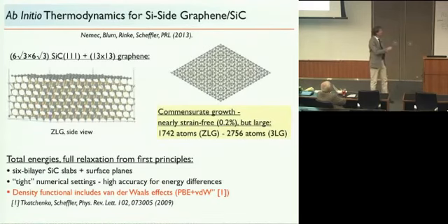So if you look at the actual unit cell that you can use for such a model, from top, you see this thing here, which is a 13 by 13 graphene plane based on a 6 square root 3 by 6 square root 3 silicon carbide model. And this is just a lot of atoms that you have to handle, even in the smallest case, 1,700 up to 2,700 atoms for the largest thing that we calculated. And that for subtle energy differences, but we can do this.